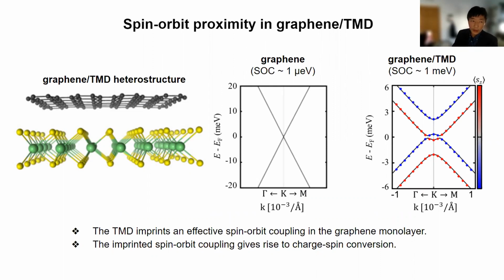graphene on TMD. We are looking at a system of twisted graphene on TMD, where this twist is assumed to be homogeneous. So this twist misorientation is assumed to be macroscopic, which people have already shown you can make, twisted 2D materials over hundreds of microns. Here is a plot of the band structure of graphene on TMD.